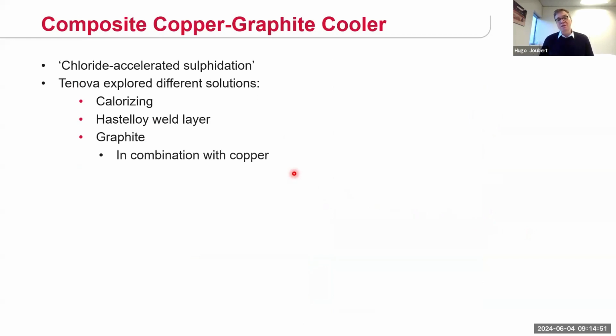So we explored quite a few different ways or potential solutions to prevent sulfidation from taking place. One is calorizing. We did a lot of test work, showed a lot of promise. Unfortunately, it didn't perform so well in the furnace itself. Hastelloy weld layer, that's something that we still use. It's quite successful. And we use it on the plate coolers on furnace number 2 now, as well as the slag tap-hole blocks for furnace 2 and for furnace 1. However, it's difficult to apply the Hastelloy on the whole cooler and cover the whole cooler surface area.